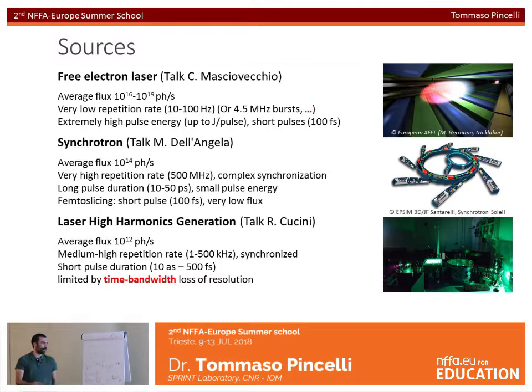And then there is laser high harmonics generation that Riccardo just explained to you. It can reach high photon fluxes, and we will see that this is kind of the limit photon flux to perform reliably time-resolved photoelectron spectroscopy. It has a medium to high repetition rate in the kilohertz range, and it's obviously synchronized because you produce the UV by the same laser that you use to pump.